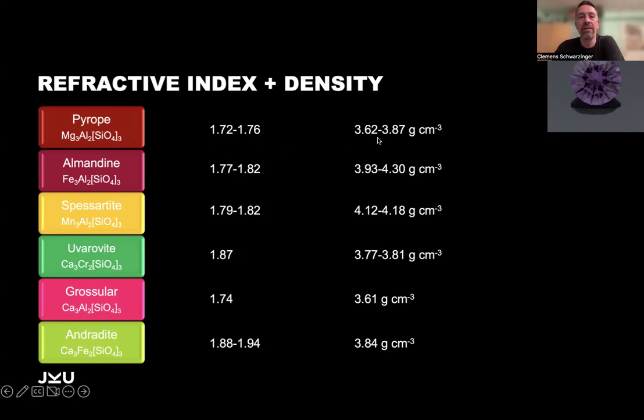The same is true with the density, ranging here from 3.6 to 3.8. This one, almandine, due to the iron, has a higher density, going up to 4.3. Also, the spessartite, 4.1 and a little bit. And the lighter ones like the grossulars, you remember the hessonite, have the lowest density of 3.6. However, first of all, measuring the density reliably is not that easy because you need at least a second digit. And then again, you have lots of these mixtures.